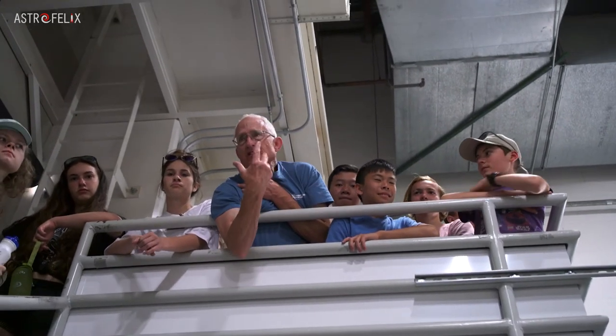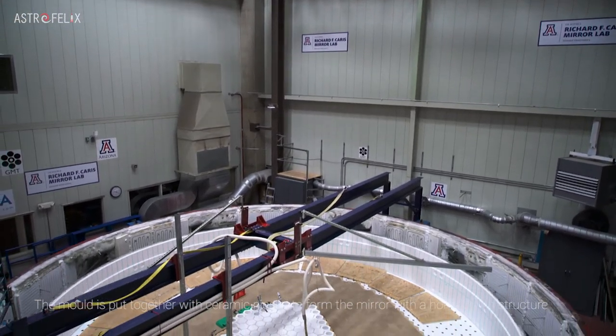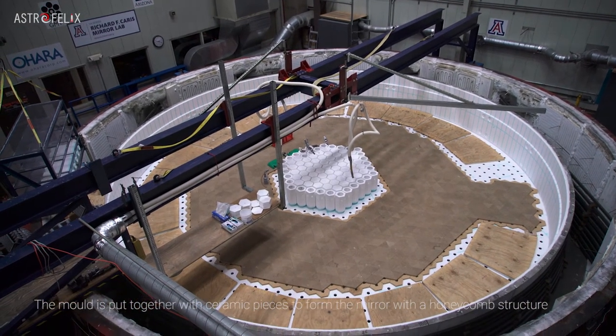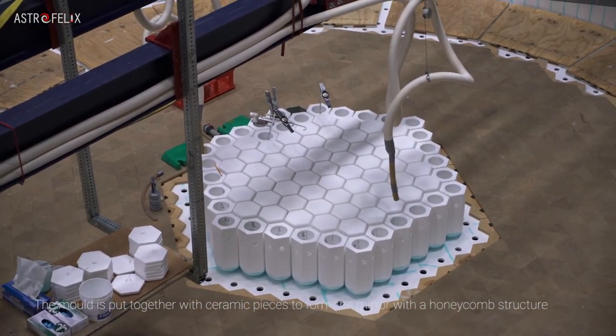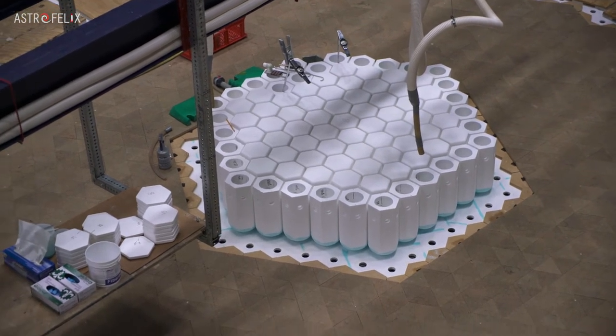This is the casting lab. There are 200 heater elements on the sides, the bottom, and on the lid, and we use electricity to heat them all up. We melt the glass while it spins, melt it for two days, and then cool it for 90 days.